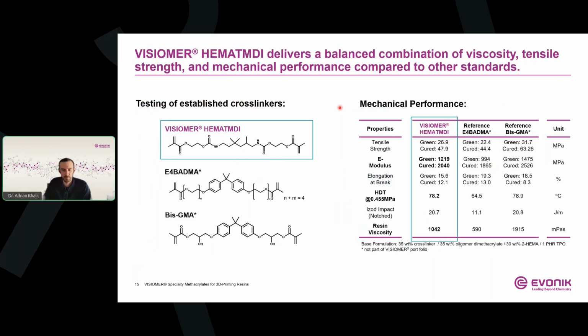So on this slide, we wanted to demonstrate how this key crosslinker, the VISIOMER HEMA-TMDI, compares against some of the most widely established benchmark materials in UV curable or photopolymer resin formulations, namely the BISGMA and the E4BADMA type crosslinker, so ethoxylated bisphenol A methacrylate crosslinker. The comparison demonstrates that the HEMA-TMDI offers a highly attractive balance between processability and the final part performance. Looking first at the viscosity,